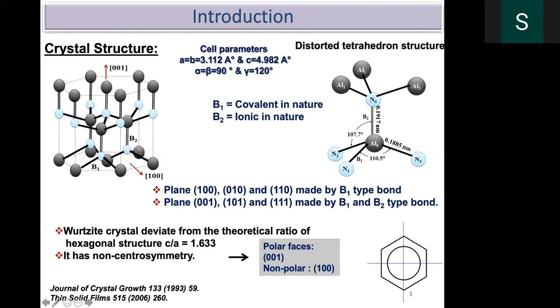See here, you can see that aluminum nitride is a hexagonal compound, which has two different kinds of bonds, B1 and B2. B1 is basically at the basal planes, and B2 predominantly at the C-axis side. B1 is covalent in nature and B2 is ionic in nature, and the covalent B1 bond is very strong. That means the basal plane is very strong.